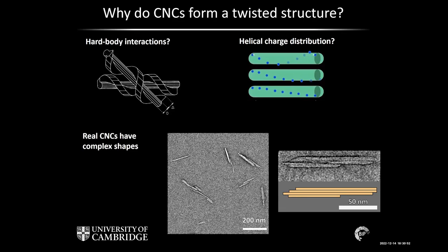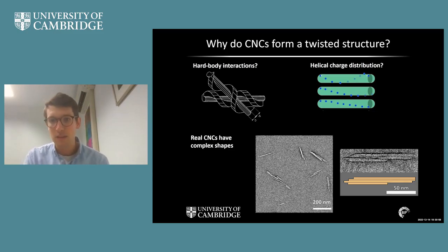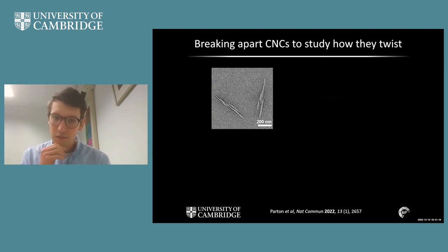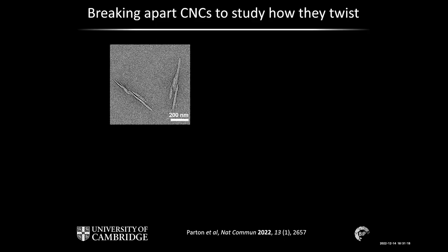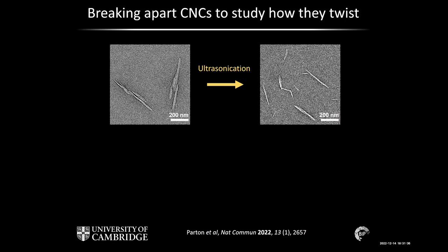So the idea that I had in my PhD was that perhaps the morphology of the CNCs was important for understanding how they assemble into this left-handed structure that we use to make these photonic pigments. And there's another piece of experimental evidence that seems to really suggest that the shape of the CNCs is important. And that's the fact that we can start from quite bundled, quite composite CNC particles, and if we apply ultrasound, so very high frequency sound at very high intensity, we can break apart these CNCs into the smaller subunits that they're made up from.